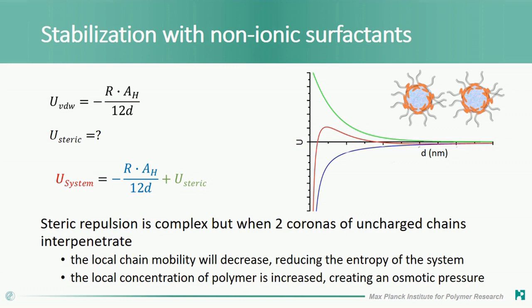But to have this effect, you need to have the right concentration of chains. For the ionic stabilization, the more you put, the better it is. When you're working with non-ionic surfactant, sometimes the more you put, it's not the better that it becomes. Although the interdigitation is becoming smaller and smaller, the stability is also decreasing, because the stability in a sterically stabilized system is due to the solvation of the chains.